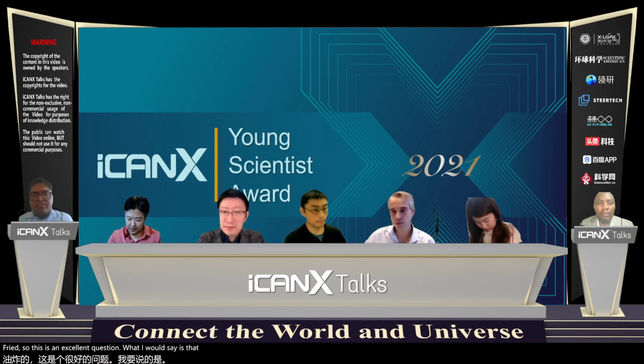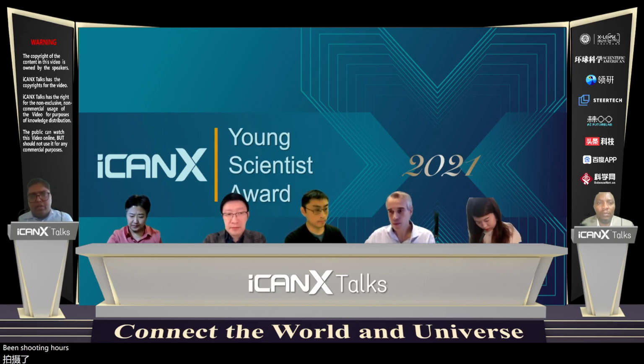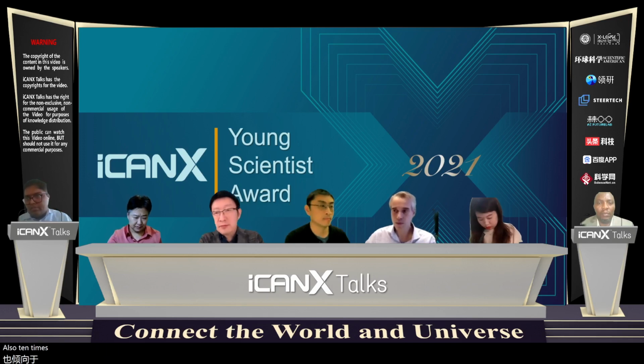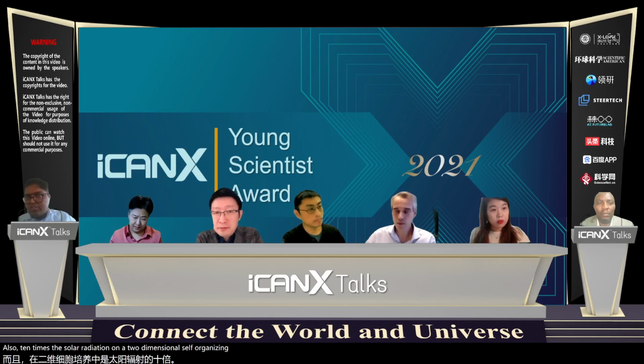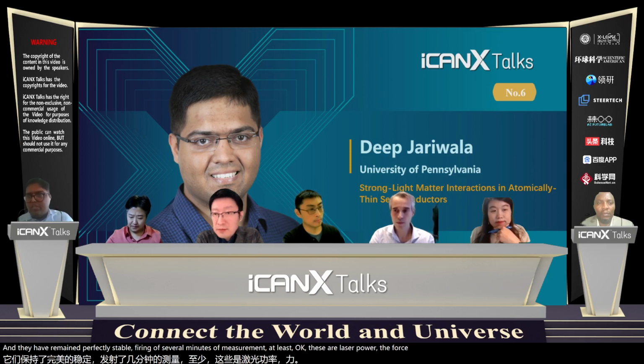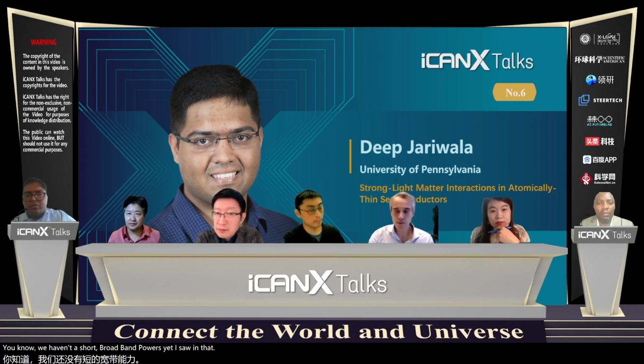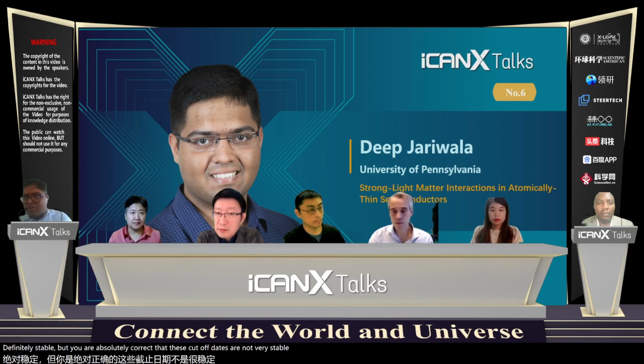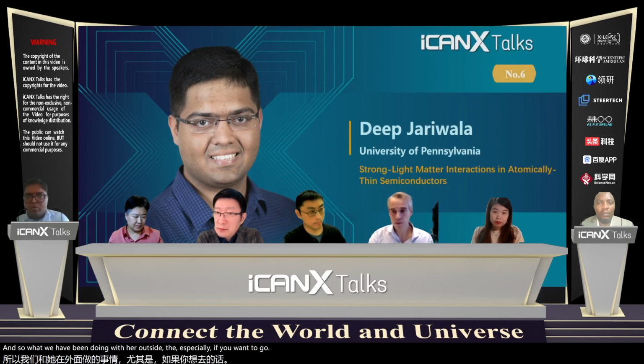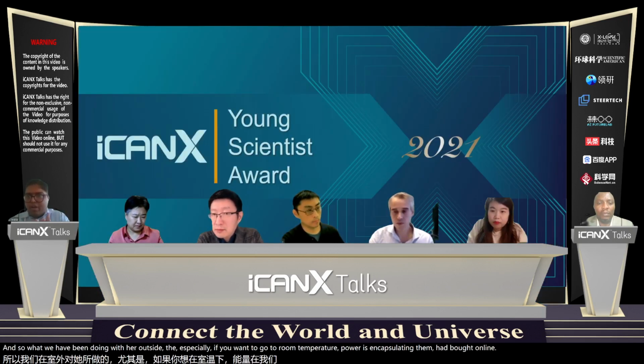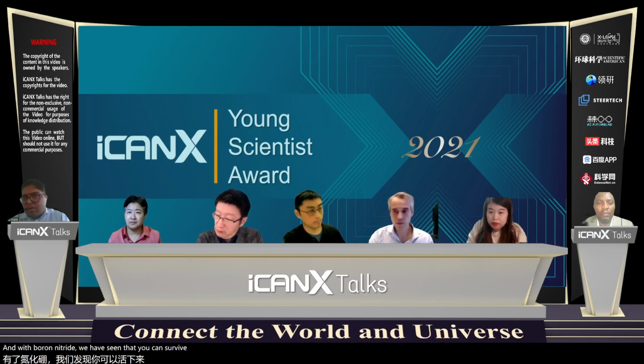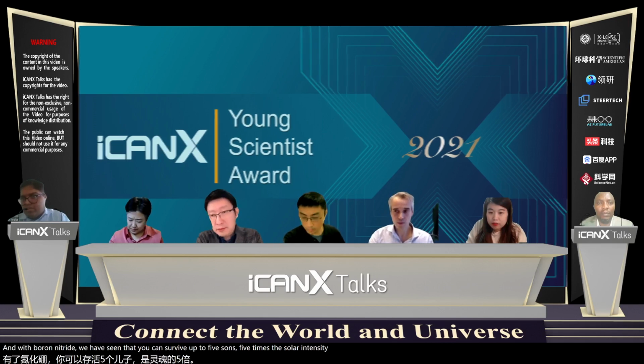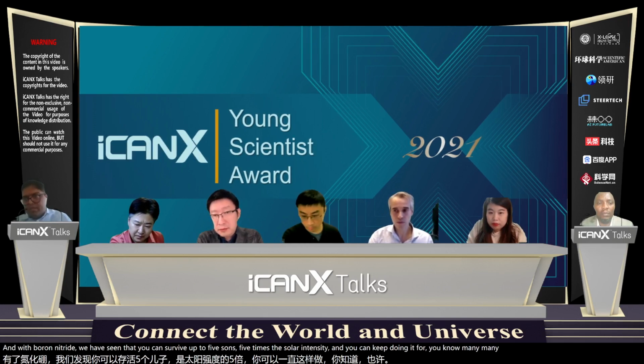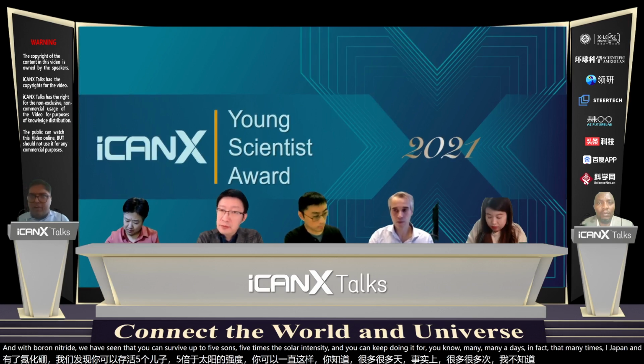What I would say is that we have been shooting powers of the order of 10 suns, so 10 times the solar radiance, on two-dimensional chalcogenides, and they have remained perfectly stable for several minutes of measurement at least. And these are laser powers, of course. We haven't shot broadband powers yet, and so in that sense, the two-dimensional chalcogenides are quite stable. But you are absolutely correct that these perovskites are not very stable. And so what we have been doing with perovskites, especially if you want to go to room temperature powers, is encapsulating them with boron nitride. And with boron nitride, we have seen that you can survive up to 5 suns, 5 times the solar intensity, and you can keep doing it for many days, in fact, and they survive fine. But yeah, if you go to 100 suns, you'll still burn them.